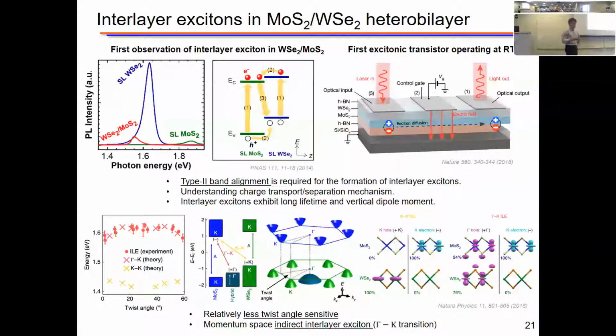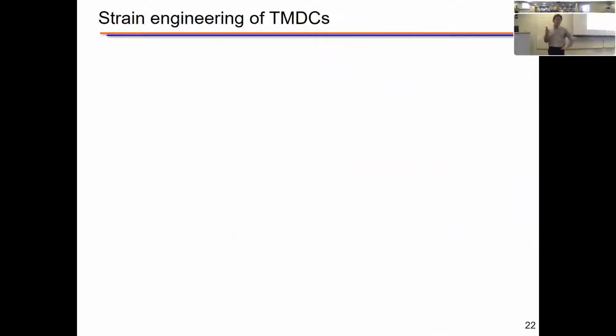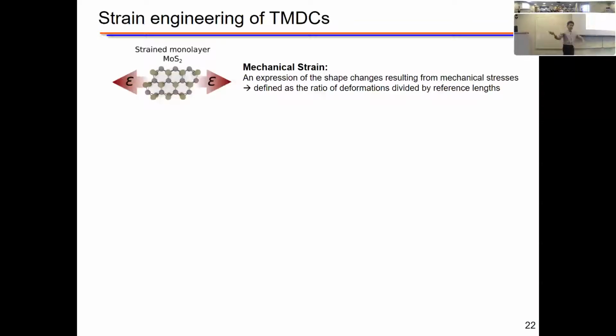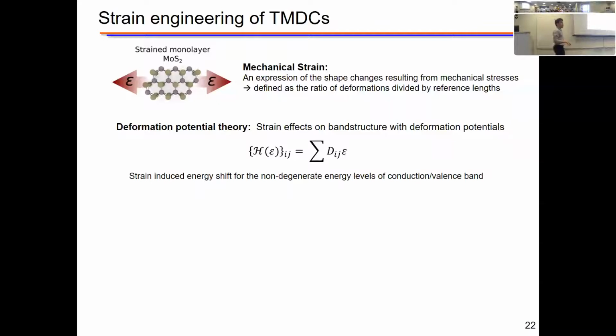With this interesting interlayer characteristic, we want to explore richer information by adding one additional tuning knob, mechanical strain. When we apply mechanical strain to a 2D material, we can change the in-plane orbital interaction, and that can change the electronic band structure. That can be described by deformation potential theory. Here, an additional Hamiltonian related to strain can be introduced, and by solving for the eigenenergy, we can get the band structure as a function of strain.